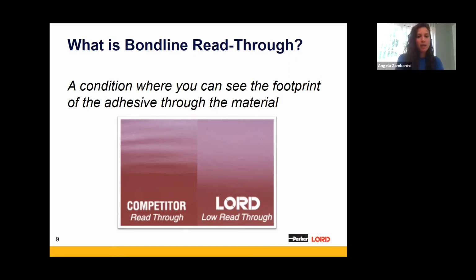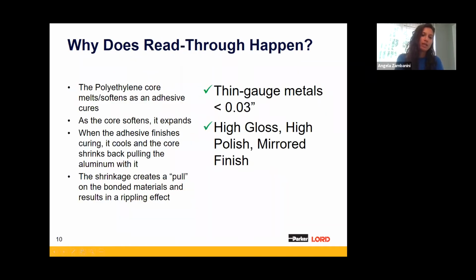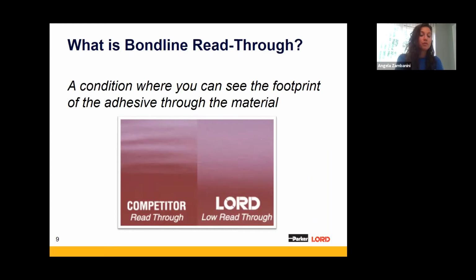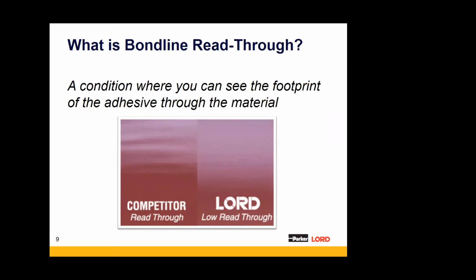So what is Bondline read-through? Bondline read-through is a condition where you can see the footprint of the adhesive through the material. To give you a visual of what that looks like, there's a picture in this slide. Essentially what we did was take an ACM panel and bond it with both a competitive adhesive as well as the Lord 810. And to the left, you can see essentially waviness, which is caused by the competitive material, whereas you don't see that same effect on the right, which has been bonded with the Lord 810.